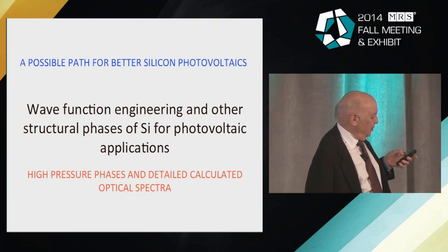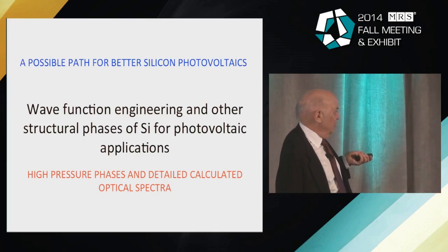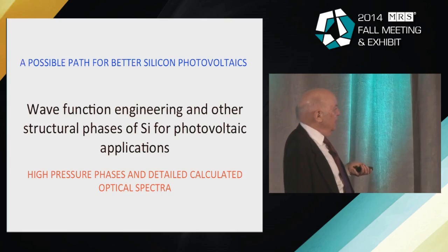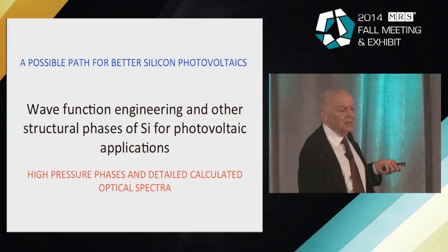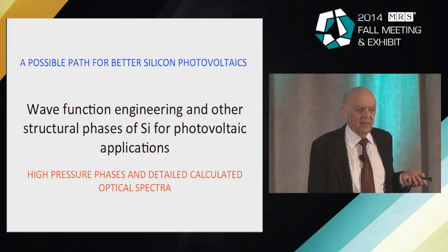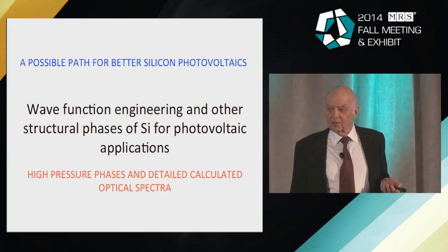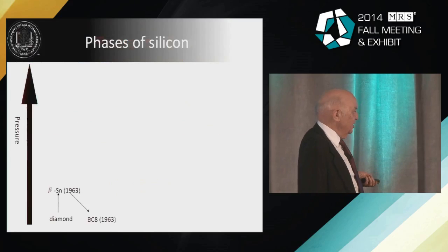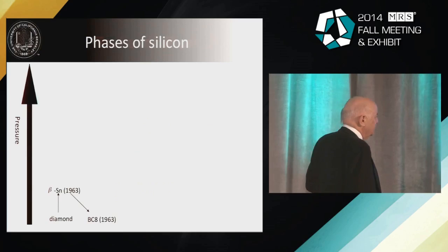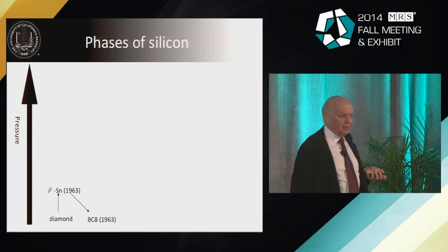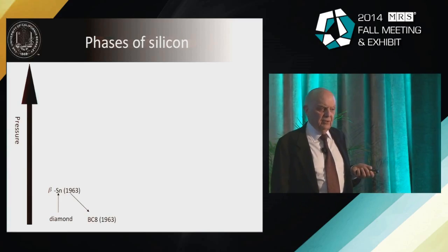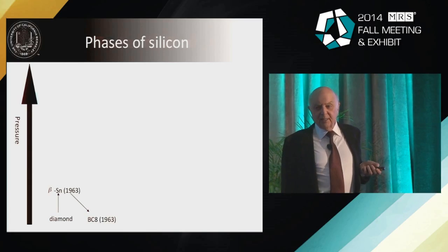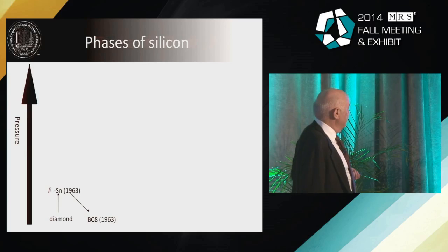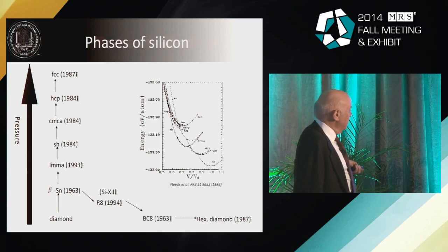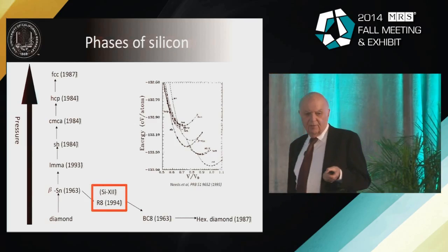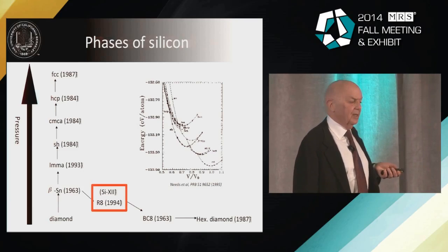However, there's another approach that's probably more important, and that is called wave function engineering. In the following sense, what I'm going to show you is an attempt to use silicon as a photovoltaic. It's the most popular photovoltaic, but put it under pressure so that you get a different structure so it's more efficient. And it's not just a question of the band gap. Now, first of all, what happens to silicon under pressure? Well, there were some high pressure phases known when these kinds of calculations started. But because of the calculations and the predictions of new structures of silicon, they have grown. And we have many, many more structures. In fact, all the theoretical structures that were predicted have been found so far.